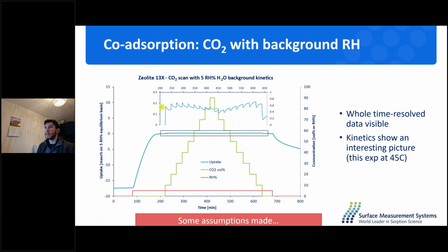So there is CO2 which does displace some of the water, but we don't really know how much. Just taking the equilibrium values here and saying that they are the uptake of CO2, as in the isotherm I've shown on the previous slide, the assumption doesn't hold anymore. Just a quick thing to note, this experiment was performed at 40C to increase the kinetics, but you can see all of this also in experiments at 25C, where all the other isotherms were recorded.